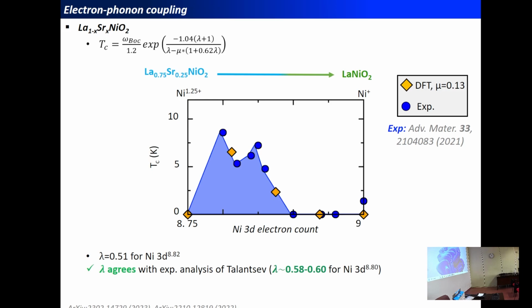And finally, using the modified McMillan equation, we can again compute the critical temperature versus the doping content. So in blue, I report the experimental value observed for the doped lanthanum nickelate. And with the orange diamonds, those are our DFT calculations using the lambda that we have fitted previously. And you see that across the different members, we reproduce nicely the behavior that is observed experimentally in these compounds.